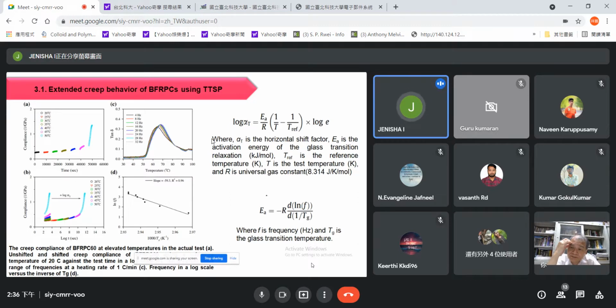So according to this, we could calculate the shift factor based on two formulas. One is the WLF equation, another one is the Arrhenius equation. We cannot use the WLF equation here because during 60 degrees Celsius to 160 degrees Celsius, it undergoes rubbery state transformation. Therefore, we use the Arrhenius plot to identify.